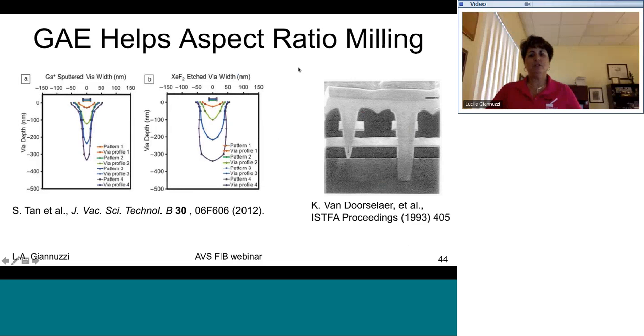And then because of the so-called reshaping that you get as a result of redeposition during milling, again, remember the shovel and dirt example before, you're going to reach a point where you're not going to be able to mill anymore. There's going to be a limit in the aspect ratio. There's going to be a limit in the depth that you can mill due to this redeposition and aspect ratio limit. Okay, so here's gallium sputtered via width as a function of different patterns.